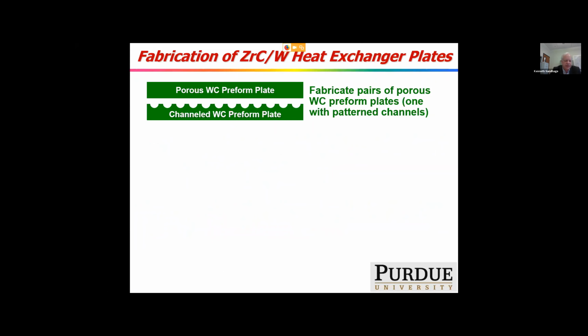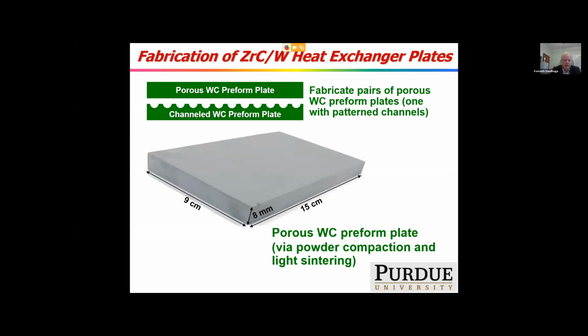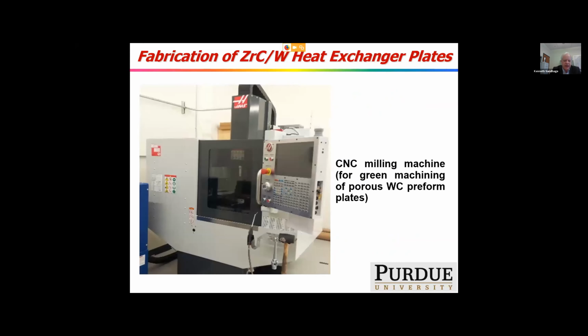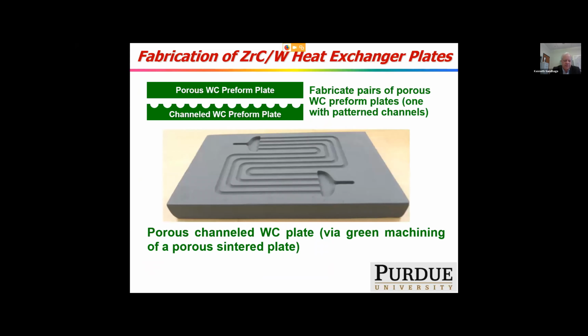So the idea is to make plates of porous tungsten carbide with channels, as well as flat plates, and then convert them into dense ZrC-tungsten plates. One way to do that is to simply compact powder into a plate shape and then green machine it, as I showed you earlier. We've done that. We actually have a CNC milling machine at Purdue to do this. And this is what it looks like. This material machines quite readily because it's 50% porous, quite friable, with standard carbide tooling.